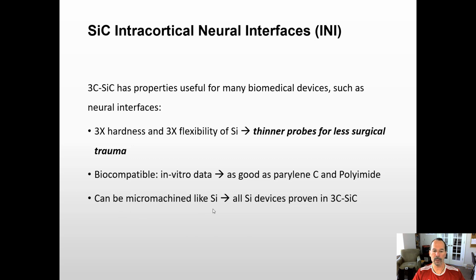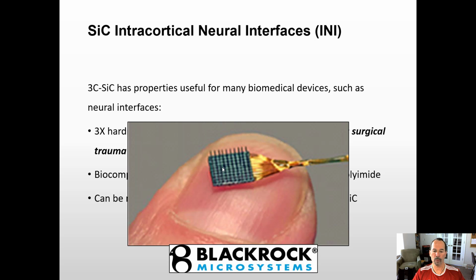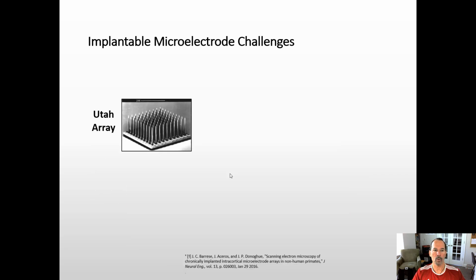We can also micromachine silicon carbide just as we do silicon. So pretty much any device, topology, architecture that's been realized in silicon, in principle, we can translate that to silicon carbide and get away from the silicon cytotoxicity problem. So here's an example of a 3D array from BlackRock using University of Utah technology. So our goal is to be able to have this type of a device available soon. So what are some of the challenges? And again, going back, this is an old photo of the University of Utah Intracortical Array. Quite important because it's the only device I believe in the US that's been FDA approved for human use for those that are chronically or terminally ill.